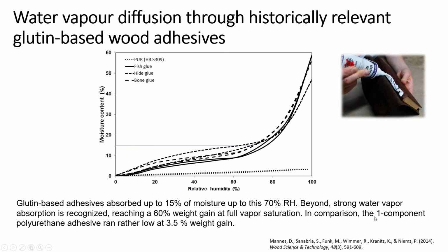A comparison is a one-component polyurethane adhesive. This is the line at the bottom here, which is almost non-responsive to vapor changes. Just a few percent are picked up as a comparison. So that was published in 2014.